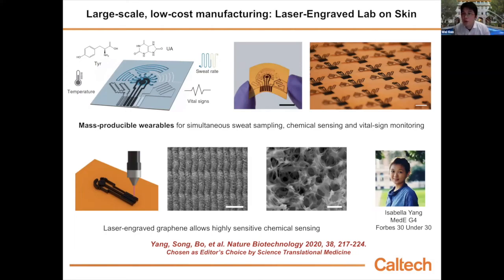So recently we proposed a laser engraving approach to prepare a multimodal microfluidic-based sweat sensor. As you can see here, by using carbon dioxide laser engraving, we can fabricate this beautiful graphene structure on the surface of polyimide. In fact, this laser engraving causes local carbonization of the polyimide surface, which makes graphene. By controlling the laser parameters, we can control the properties of this graphene composite. Based on this graphene, we can develop high performance chemical sensors and physical sensors.